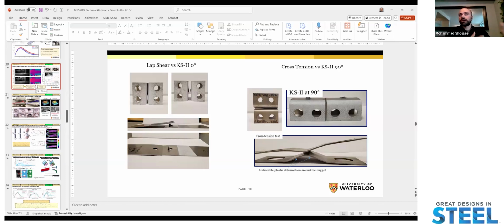So the idealized shape of the failure loci in shear tensile loading is much closer to the one that we have after accounting for all the orientations in those cases. But the situation gets much worse in softer steels, such as the 3G 980. We have all the data for the PHS as well. We have published part of it, but this was not included in this presentation, the data for PHS.